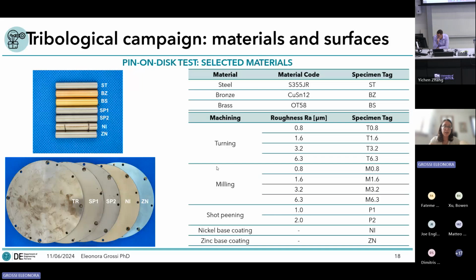For the disc, I selected 2 different machining processes, which is turning and milling, obtaining 4 different roughness values each. Then I investigated the shot peening, which increased the superficial hardness of the steel. And finally, I investigated 2 different coatings, nickel base and zinc base.